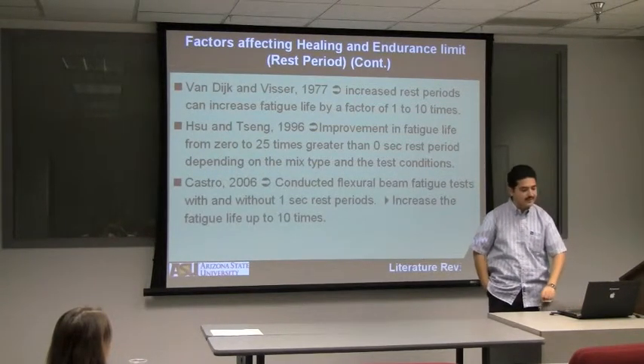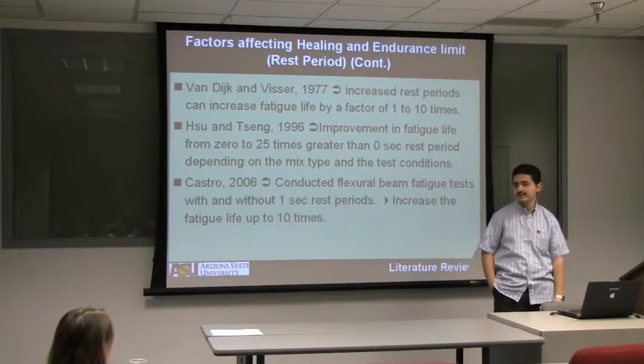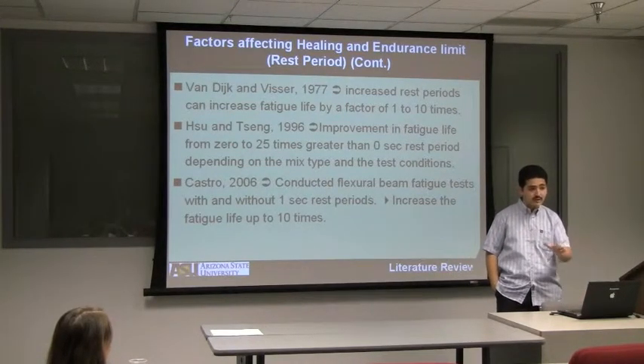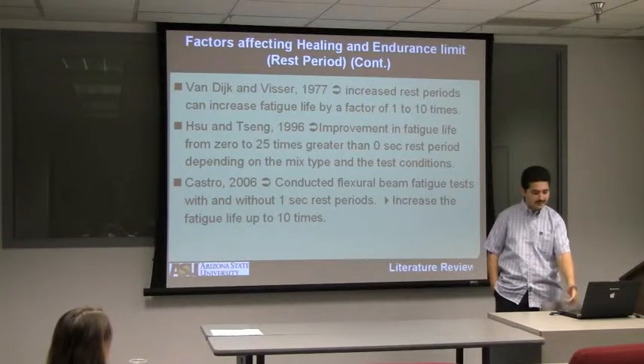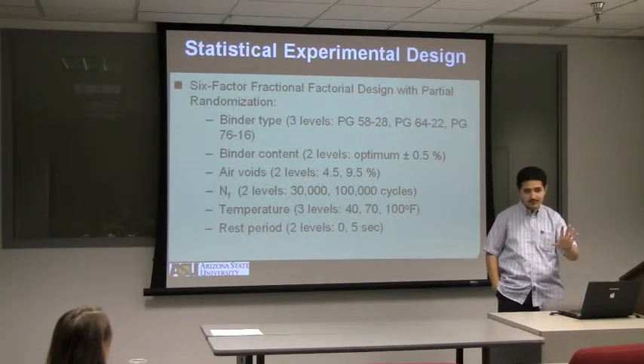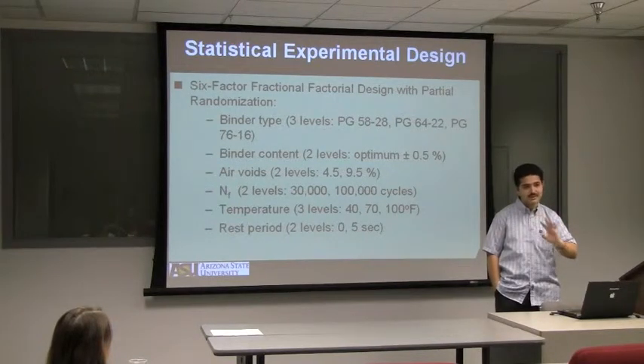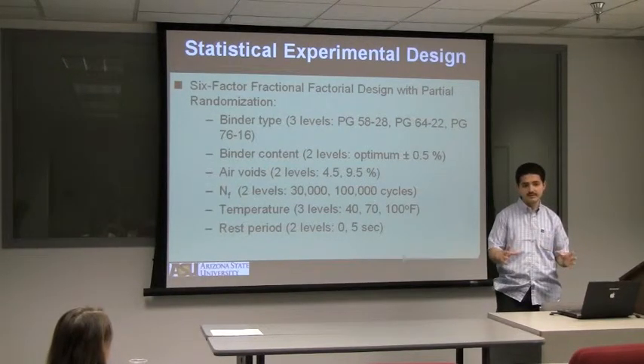And lastly, Castro also conducted the flexural beam fatigue test with and without 1 second rest period, and he had an increase in the fatigue life up to 10 times. So done with the literature, now I know exactly what's going on, what other people did, and now I was confident to build my statistical program or statistical experimental design.